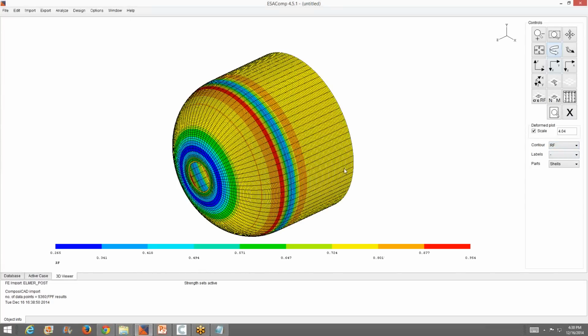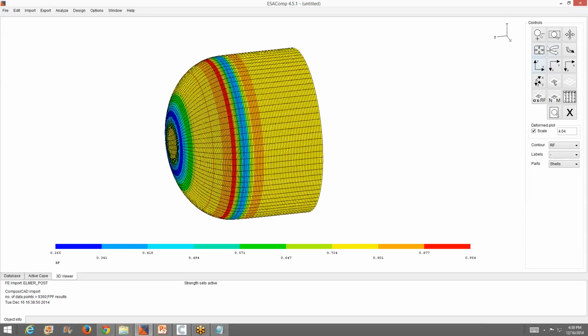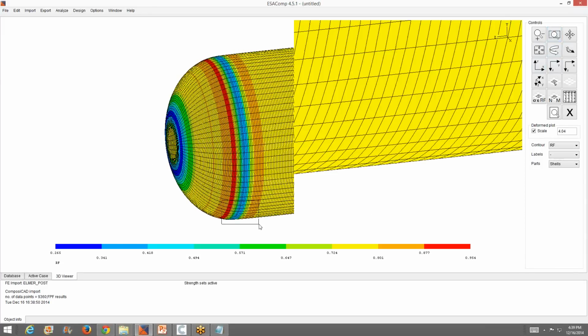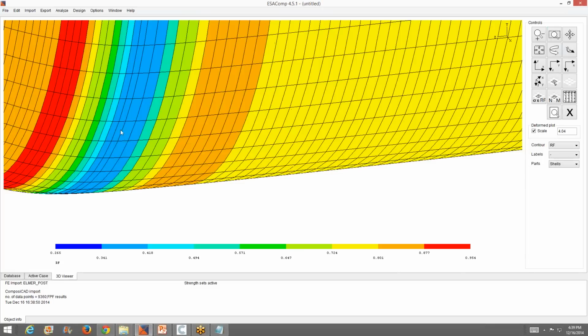And now we have a clear indication that this region is a potential location for failure due to the high out-of-plane shear stresses. So potentially these high out-of-plane shear stresses induce delamination, and delamination increases, and that makes the tank fail during cyclic loading.